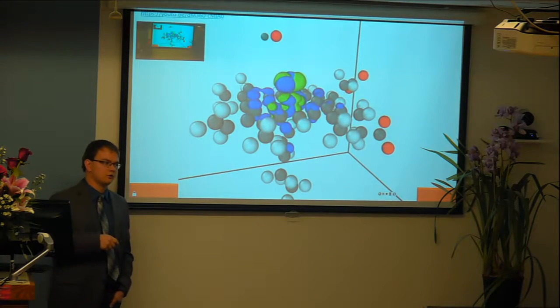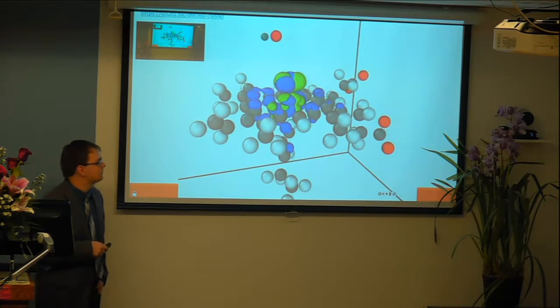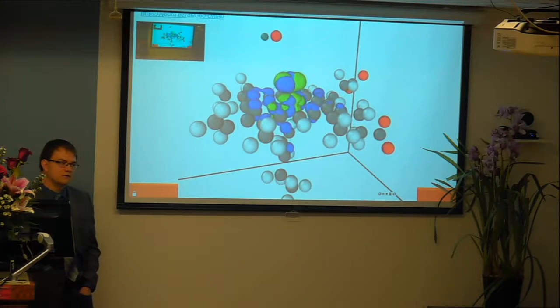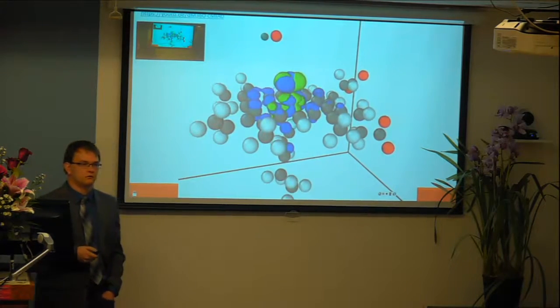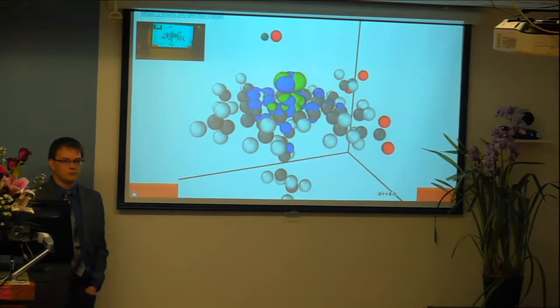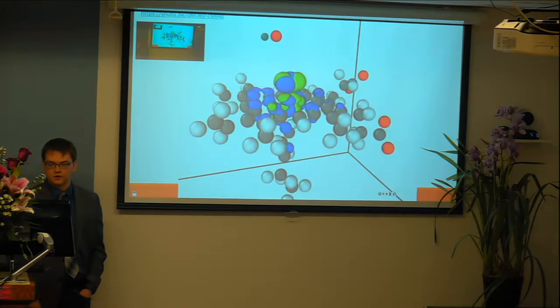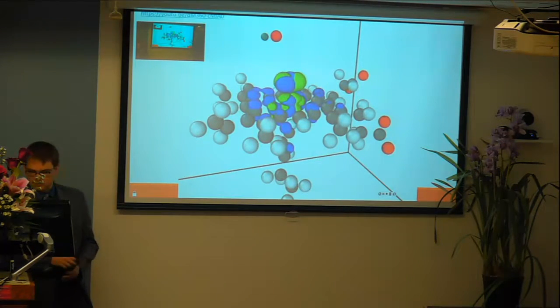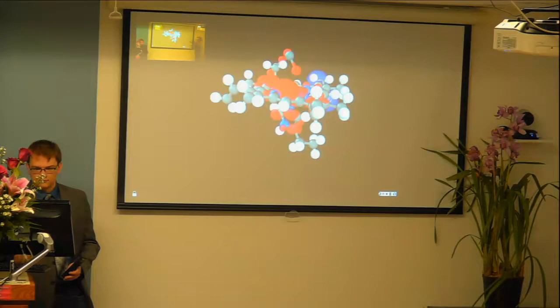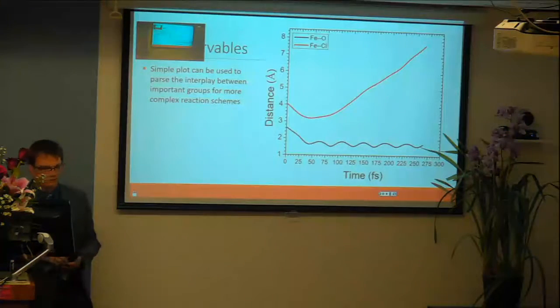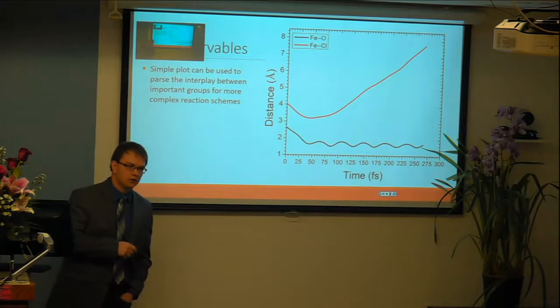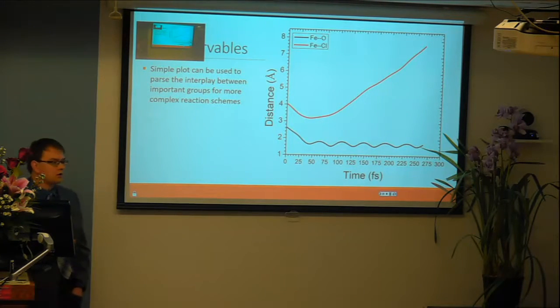And also the time step in the molecular dynamics should be reduced. Currently it's at 1 femtosecond. For reaction type processes, this should most likely be reduced to gain better electronic convergence between steps. Like I said earlier, this is more or less a meaningless plot, but you can make a lot of interesting plots.